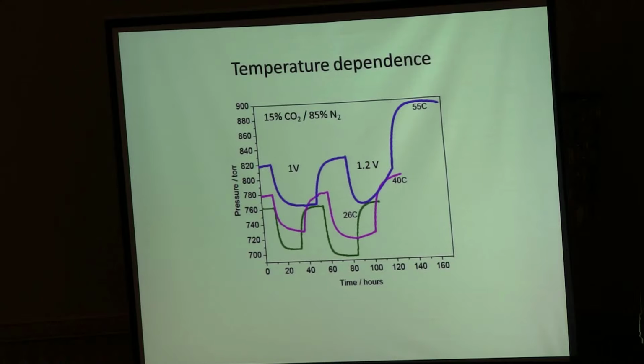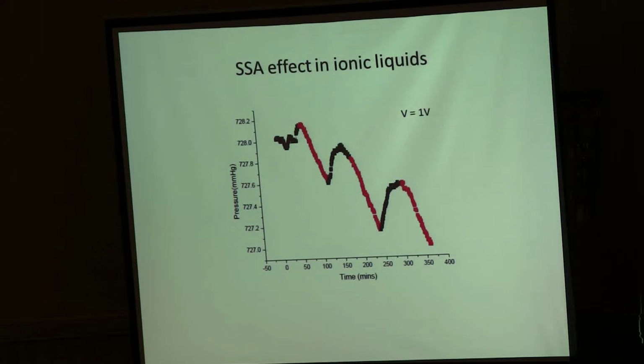So probably at 1.2 volts, you already start to have electrolytic decomposition, and that means that you produce gas. That is also further indicated by the fact that at the end of the experiment, your pressure is higher than in the beginning of the experiment. Finally, we were also interested in the question, can we do such experiments only in aqueous electrolytes or also in other electrolytes? So we also did preliminary experiments in ionic liquid, and you see qualitatively the same. As we charge our capacitor, the pressure goes down. As we discharge the capacitor, our pressure goes up.